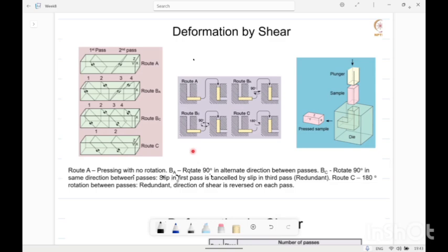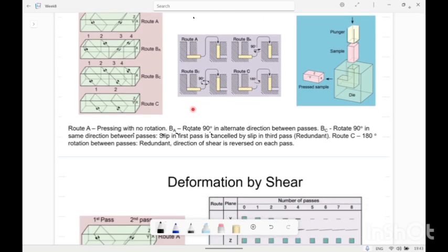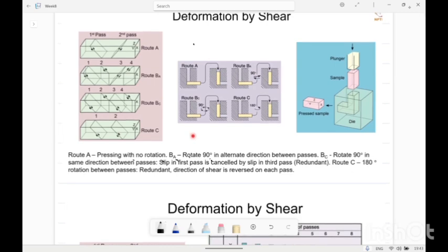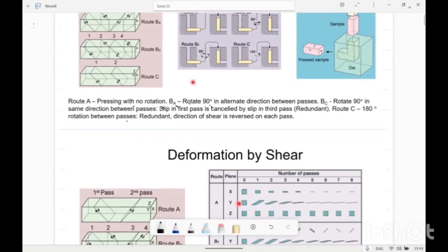That leads to the slip in the first pass being cancelled by the slip in the third pass. That I will explain in a while. In route C, the 180 degree rotation is done between passes, that is redundant, meaning the direction of shear is reversed on each pass.